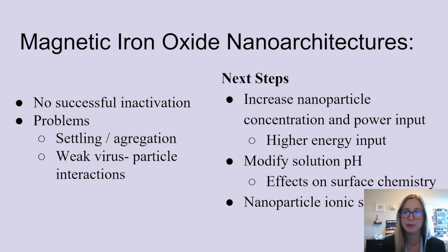For the first round of experiments, we used a commercially available iron nanoparticle with MS2. Initially, we were unable to observe any disinfection or really much of an impact, but we did notice some problems. During the attempt, we noticed that particles settle quickly to the bottom of solution. This is a problem because the chances of the viruses interacting with the localized heating on the particles is much greater when the particles are suspended in solution rather than settled and collected at the bottom. This is likely due to the large size of the nanoparticles, and even though the particles did generate heat, it wasn't interacting directly with the viruses and causing disinfection.